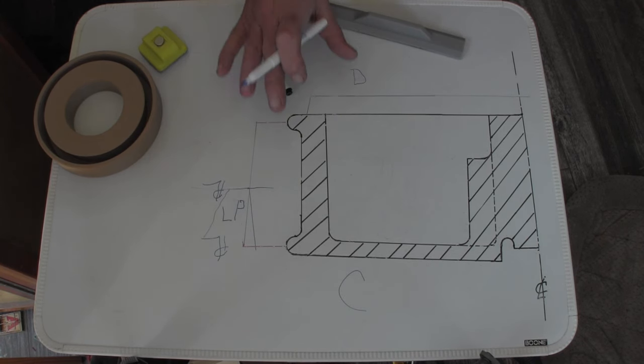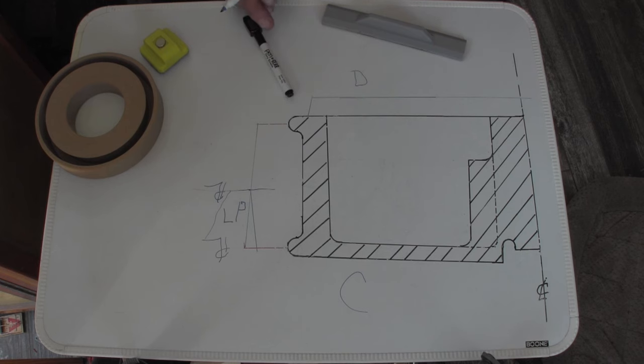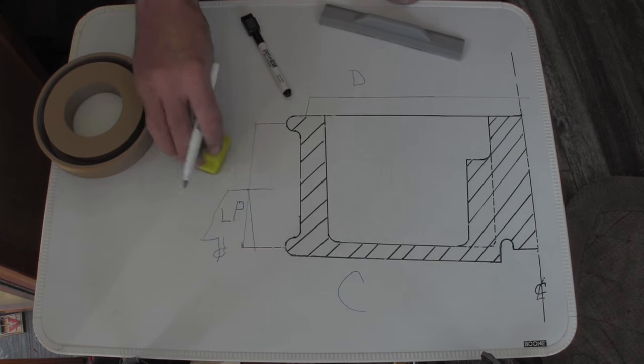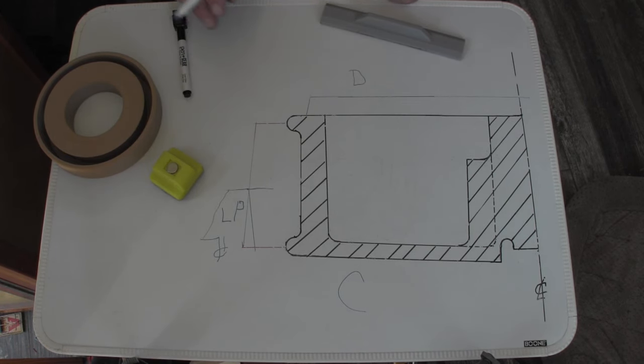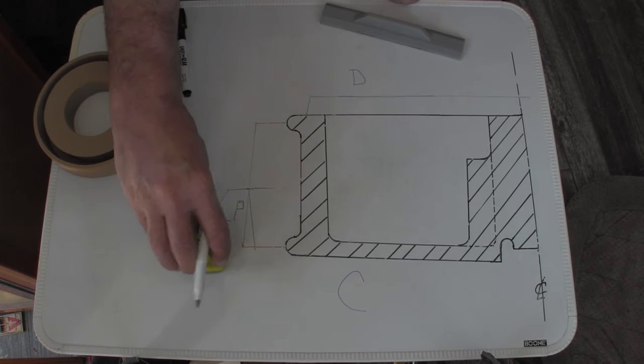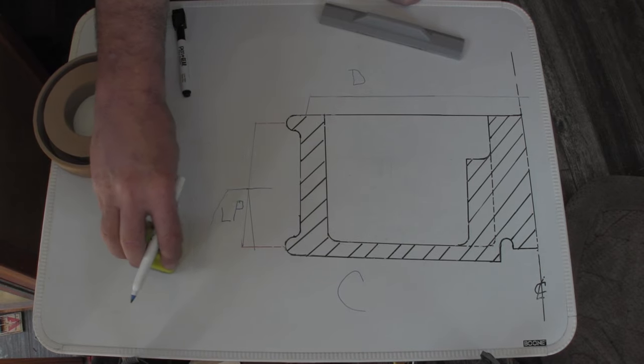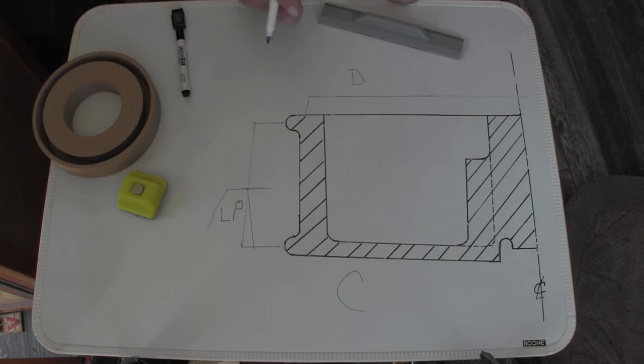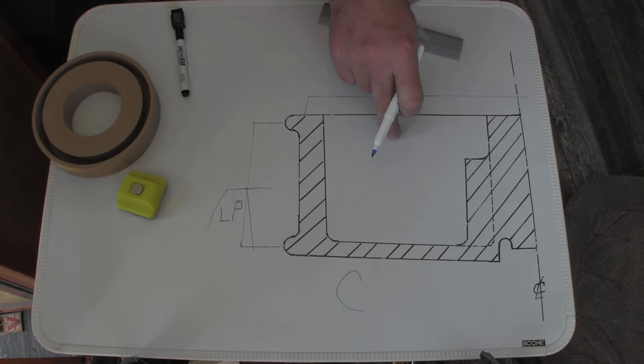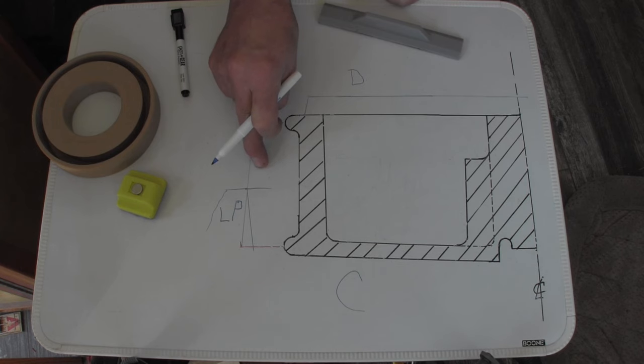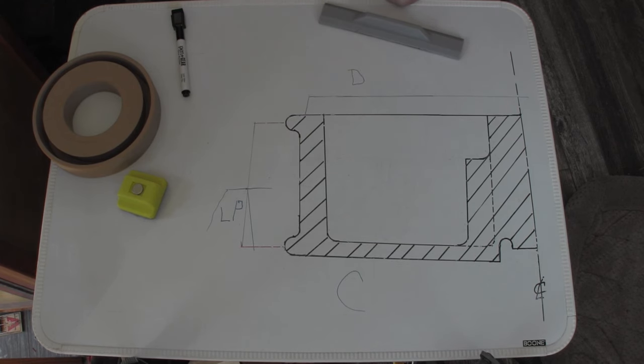So everything's going to come out that way. The loose piece would come out first. And you do it, lift it out. I didn't really like that, but it's a possibility. The reason I didn't like it is you're just making the job a bit more complicated. You still got, if you got a core here, you can split it this way on the outside ring. But what if you don't want to use the outside ring?